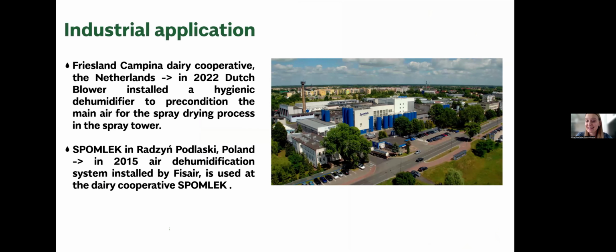I would like to mention one last thing, the industrial application. What we know from the literature about application of these methods, so air dehumidification system, we know that in 2 dairy cooperatives in Europe, in the Netherlands, in Poland, they for quite some time are using air dehumidification system for their spray drying towers. However, what we do not know from the literature is whether they are really using it to lower drying temperature. Most likely they're using it to control the humidity of drying air, not necessarily to modify the drying parameters. And as you can see over here, we do not find literature on application of air dehumidification in, let's say, production of fruit powders, vegetable powders, so the sugar-rich materials that are really difficult to be dried.